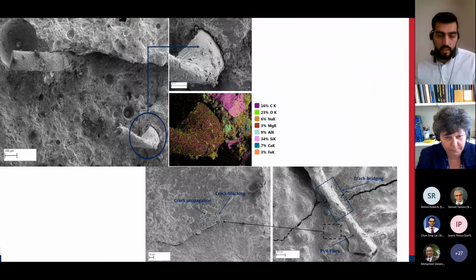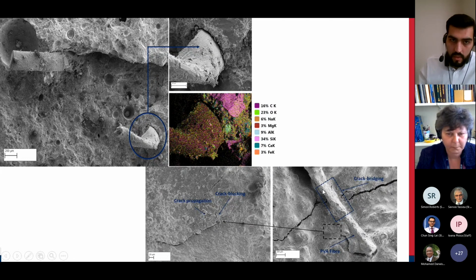We looked at the microstructure. The SEM images here are showing us the PVA fiber and the interface of the binder, the low carbon binders and the fibers, and how the cracks have been arrested or blocked because of the presence of these fibers. So this is why the flexural strength is as high as it is, and as high as I showed you in the previous slide.